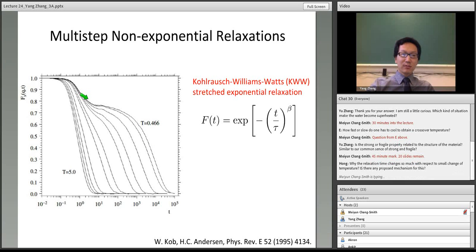Okay, so the appearance of beta relaxation is very intriguing. We have a lot of explanations for why this is happening, but there's still no agreement on what the final theory should be to explain these multi-step non-exponential relaxations. For example, mode-coupling theory explains this as being due to caging. At low temperatures, all the atoms form cages. In order for one particle to relax or to diffuse, the cage has to break, and this is related to the caging effect.